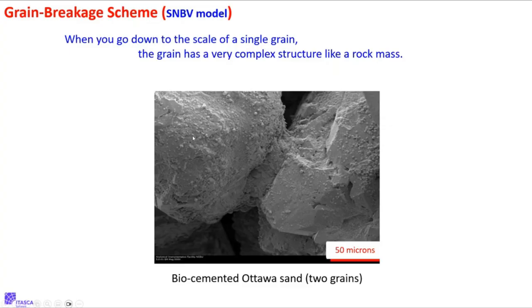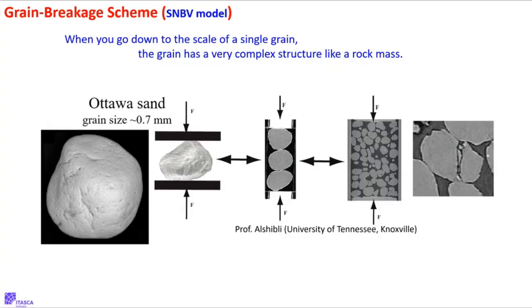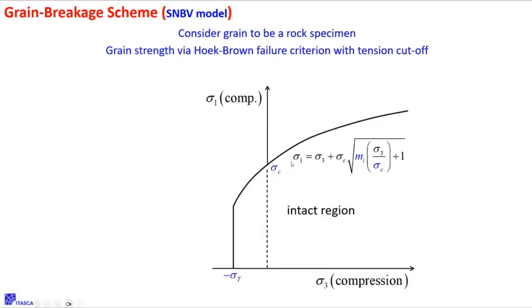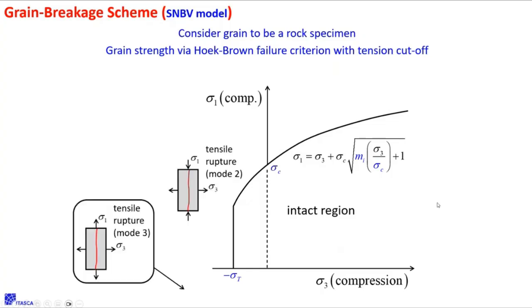If I did that for rock specimens, I'd get a strength envelope, a Hoek-Brown strength envelope. We talked a little bit about this. This is stress sigma 1, sigma 3 space, principal stress space. This is the strength in the triaxial test. That's a UCS test. If you apply compression, it gets stronger. This is the tensile strength. And so I'm going to assume that it fits this. So there are going to be 3 parameters in my breakage model. These are the Hoek-Brown parameters. This is the Hoek-Brown equation. It has an m, it has a UCS, it has a tensile strength. Okay. And so this is what we're doing in our model.